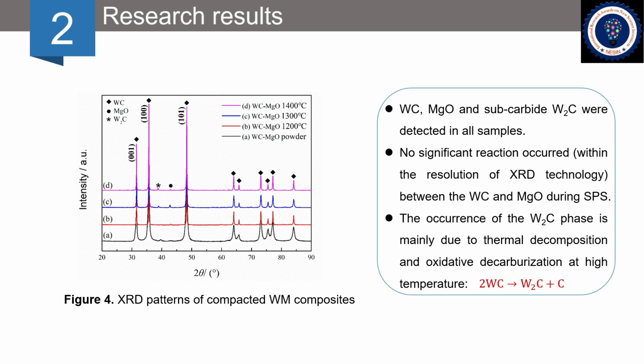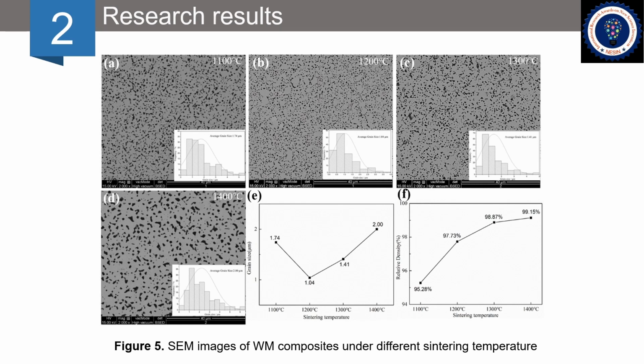The occurrence of the tungsten carbide phase is mainly due to decomposition and oxidative decarburization at high temperature by the following equation. Figure 5 displayed typical microstructure for WM composites sintered at 1100 degrees, 1200 degrees, 1300 degrees, and 1400 degrees with corresponding average tungsten carbide grain size.